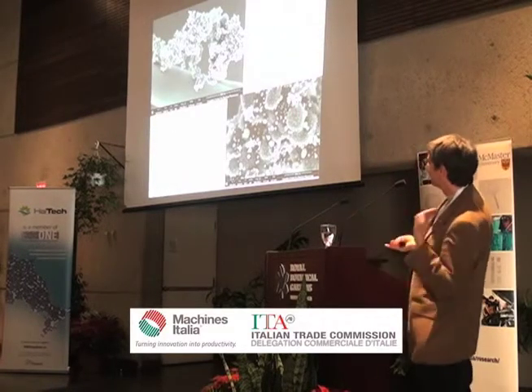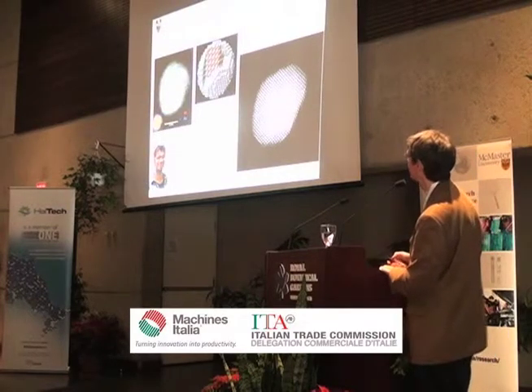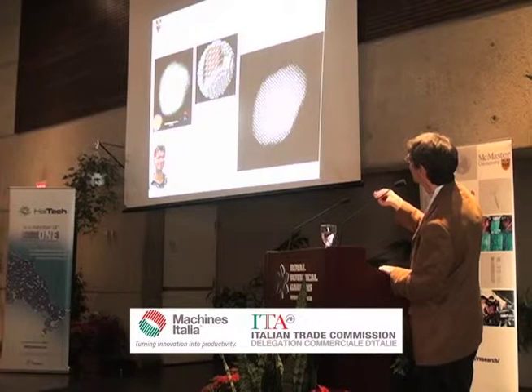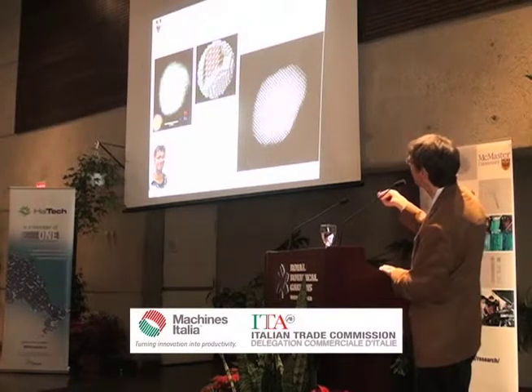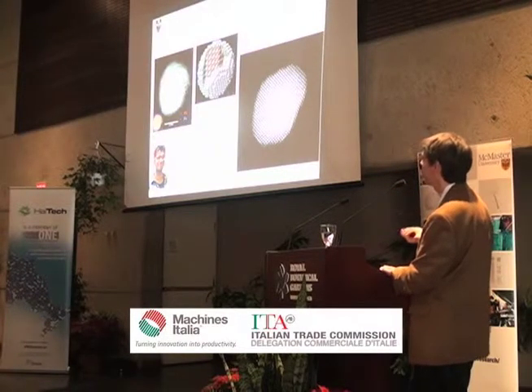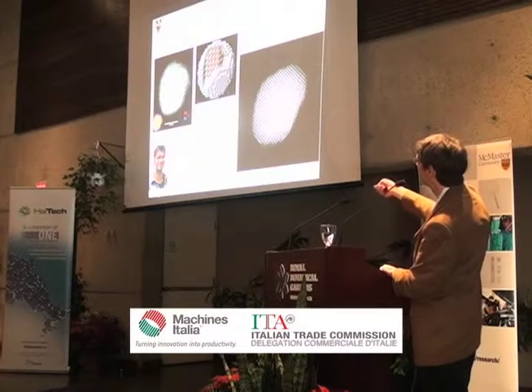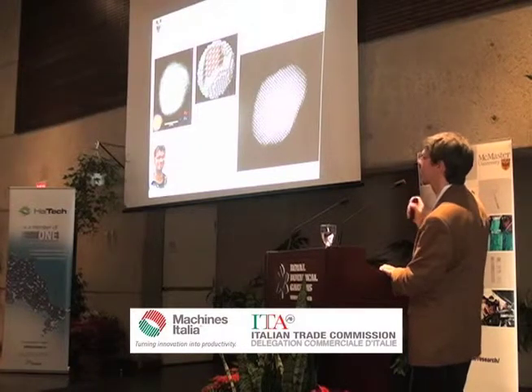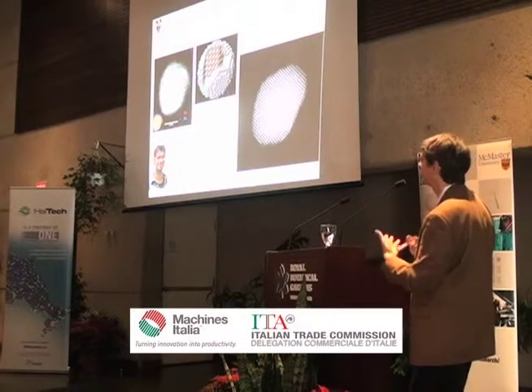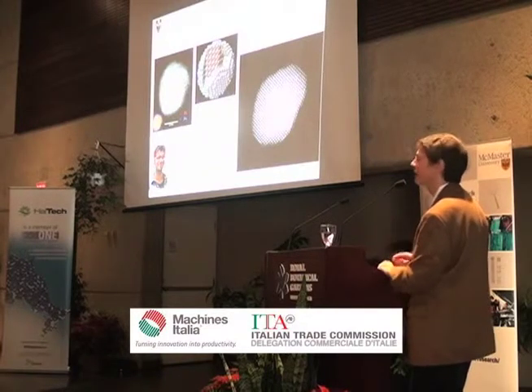If you go to higher resolution with a transmission microscope, then you can actually see the atoms. So these dots are atoms, and the bright dots are platinum atoms, and the darker areas in between these bright dots, the blue ones in this diagram, are actually iron atoms. So what you can do is produce a lot of platinum atoms on the surface with minimal waste of platinum atoms in the core because you use iron. Iron is not very expensive. And so these images provide this kind of information.